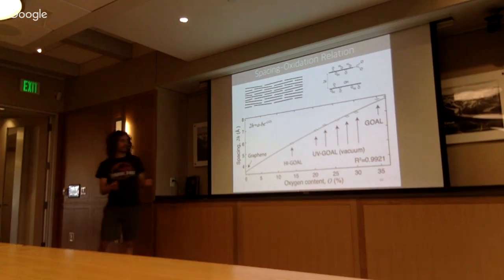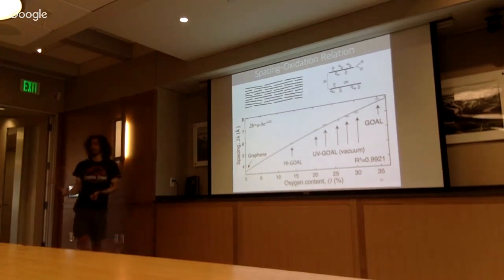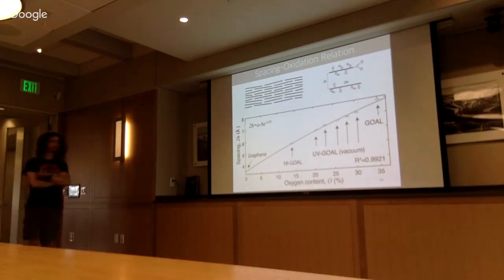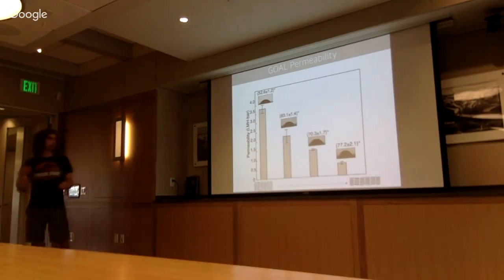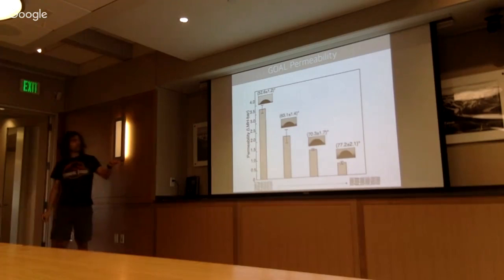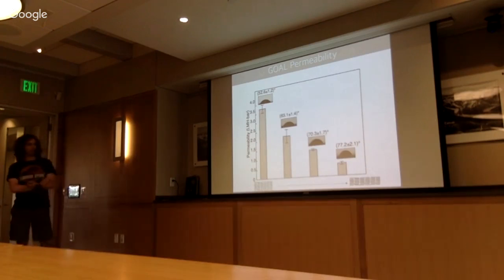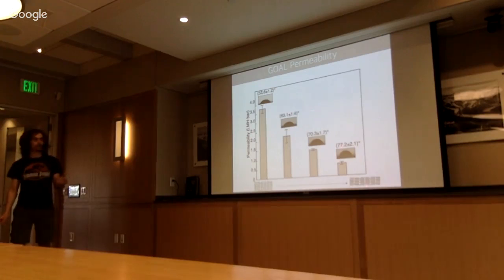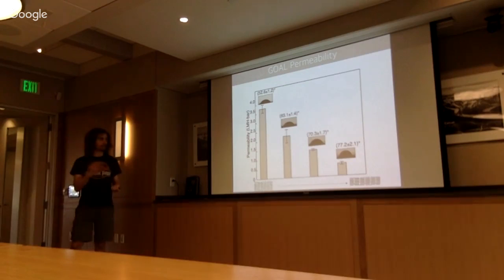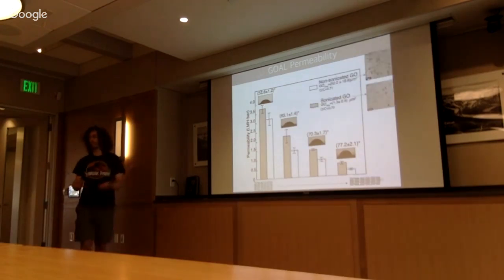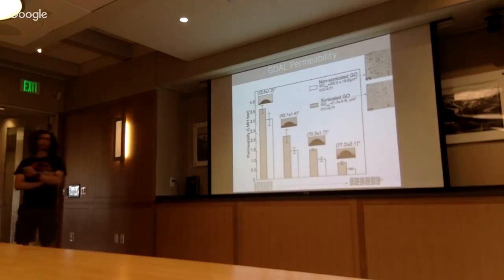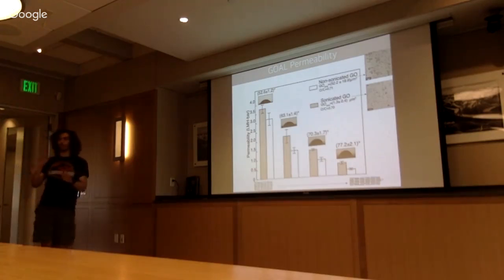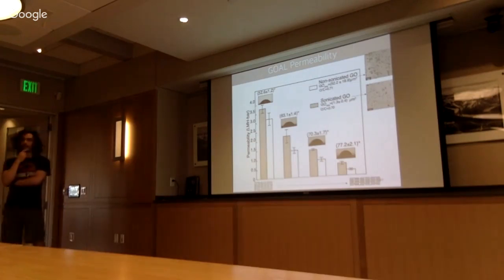And also what this tells us is that instead of calculating the oxygen content through XPS, I can just do XRD and obtain the oxygen content, or vice versa. So we are really speeding up the characterization process of this material. But let's see how the water transport is modified when we go from this structure to that structure. We see that the water transport, expressed as permeability, changes dramatically from 3.5 to about 0.5 LMH per bar, and also the hydrophobicity changes, and hydrophobicity is captured with contact angle, so we obtain a more hydrophobic structure. But when we tried to change the flake size, on the other hand, we did not see a big change in the permeability. So what does this mean? That basically what really controls the water transport in this material is the separation distance, as was proven by simulations before.